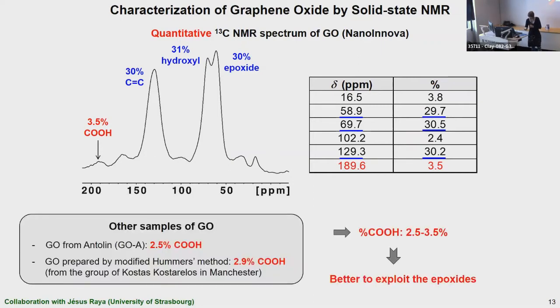We then extended the characterization to other sources of graphene oxide. So this was graphene oxide from the NanoInnova Spanish company. We also characterized another commercially available graphene oxide from the Antolin Spanish company. And we found that there were 2.5% of carboxylic acids.